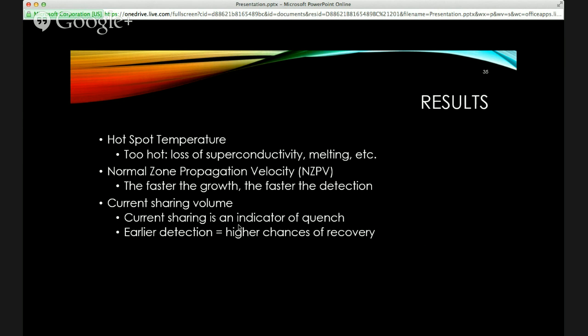I wanted to look at that hotspot temperature. We want to avoid what we saw in that quench picture. If it's too hot, you not only lose superconductivity, but you can also melt, as we saw there, and burn. And if it's large enough and you lose your superconductivity, you have to expel this amount of energy somewhere, which can destroy an expensive magnet, or you expel this energy to the point it could be dangerous.